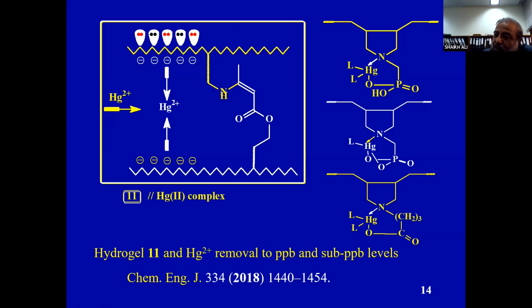We do that because people can remove a lot of mercury and lead at high concentration, but we are working for low concentration. And the World Health Organization says that in future we want mercury not ppb, even 0 ppb. So here we are trying to use that hydrogel to remove mercury, and it can remove to ppb and sub ppb levels. That is the WHO goal. And this has done a tremendous job with so many minus charges here, from phosphonate, carboxylate, and you have sulfonate, and you have CO2 minus in another chain, and they can all augment this capturing of mercury, and we have been able to get it down to sub ppb levels.